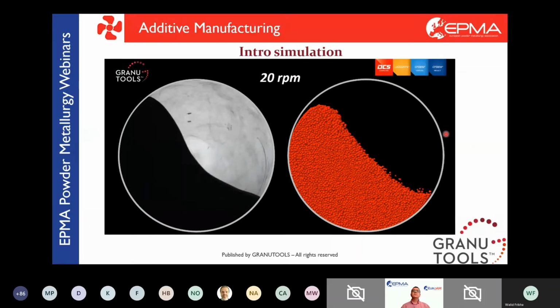When it comes to the test with the GranuDrum, since the goal is to match the interface as best as you can, there is only one set of parameters that will give you a perfect match, and this perfect match may be perfect at 20 RPM but not at 60 RPM. So you need to find a set of parameters that will match the best at several speeds. So this is a way to prove your model even further, and to really give a model that will behave the same as the powder inside the drum.